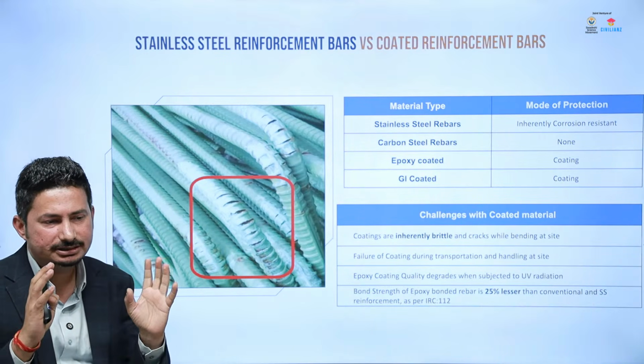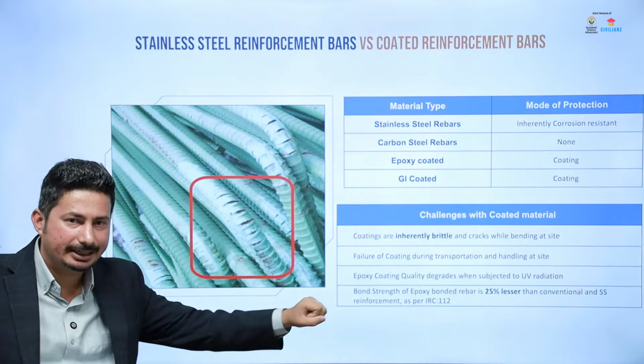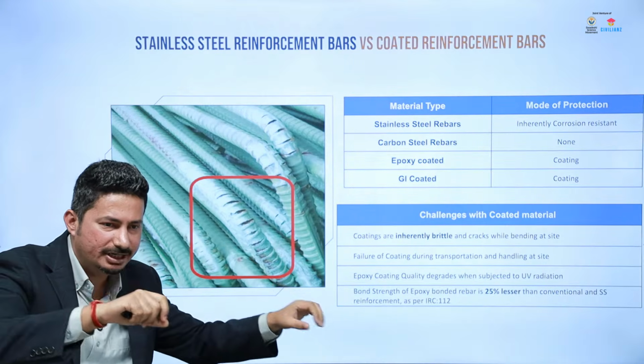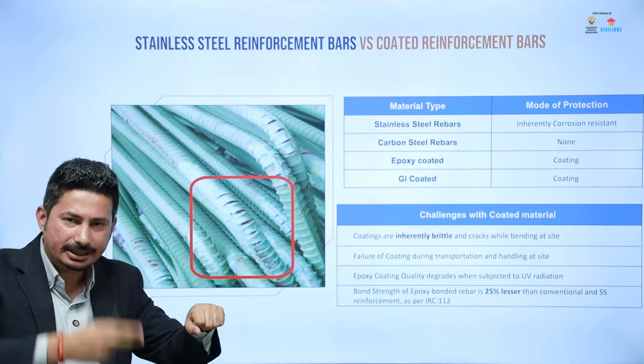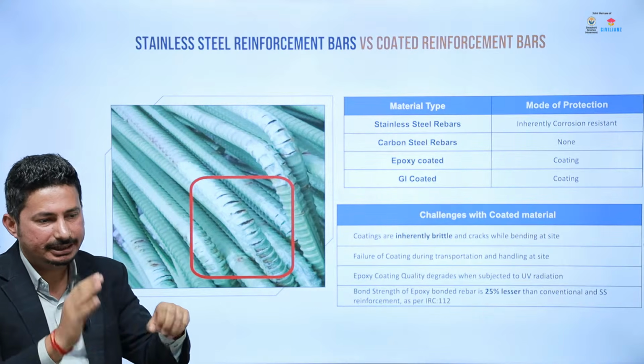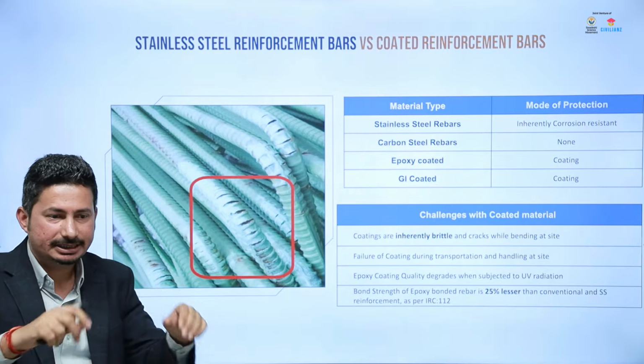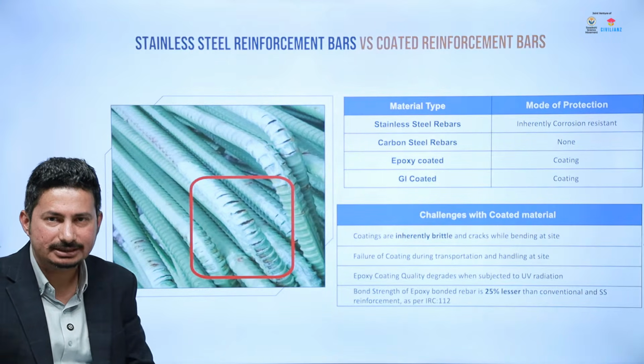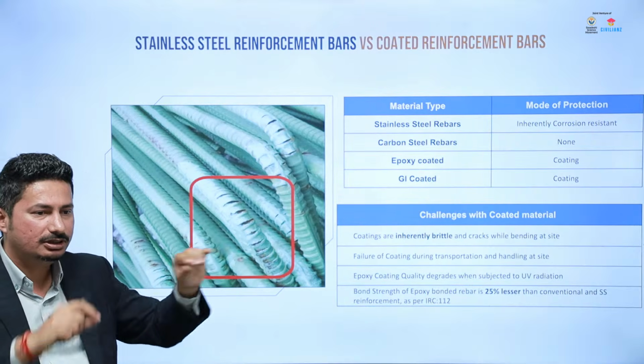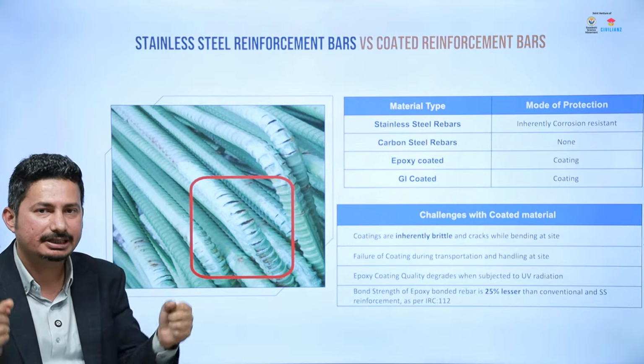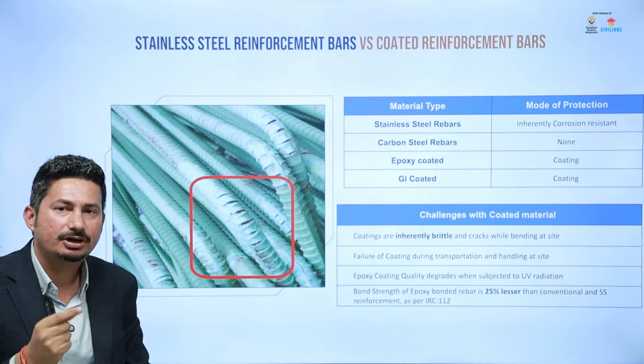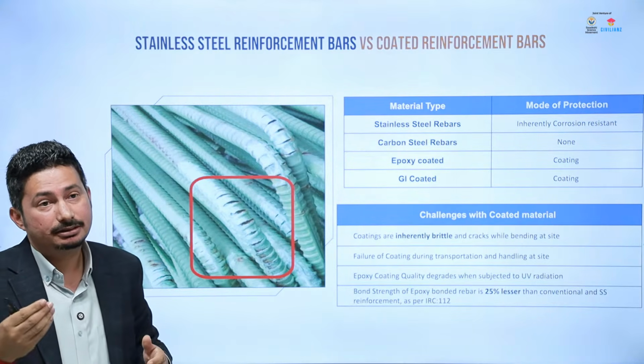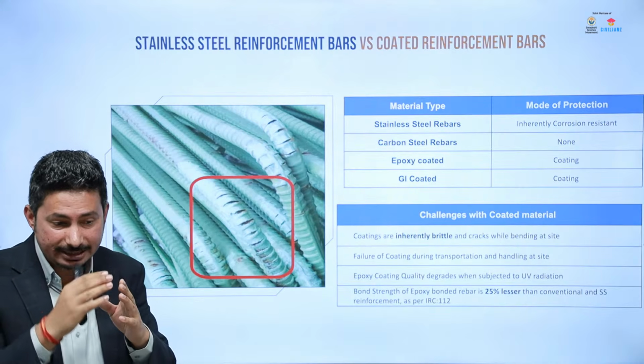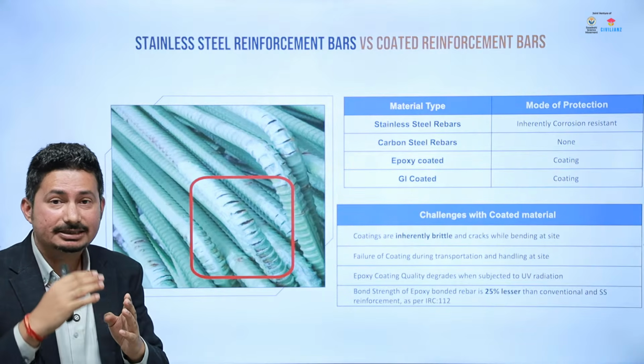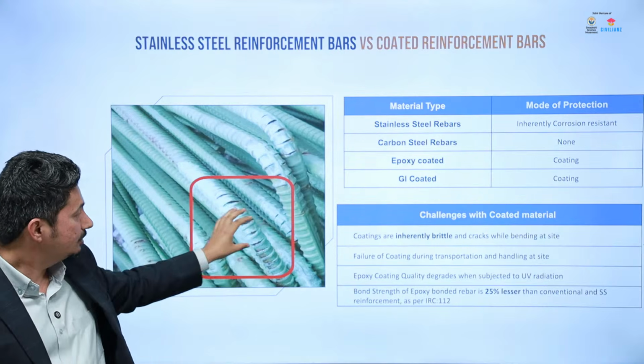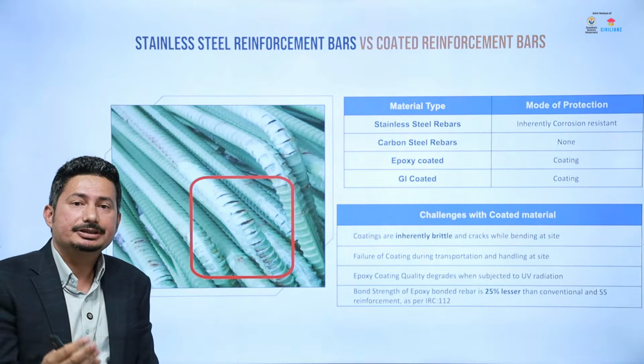Now, we have to understand that all these coated rebars are made in a straight line in the factory. The moment we bring them to the site, the first thing is we have to cut them. The moment we cut the rebars, the surface gets exposed. The second operation is to bend them. The moment we bend them, cracks will develop, because all these coatings will crack when we bend the rebars. Therefore, the efficacy of coatings will not be better. And also, with these cracks developing in the coating, accelerated corrosion happens in these concentrated areas, which is even worse than uniform corrosion.